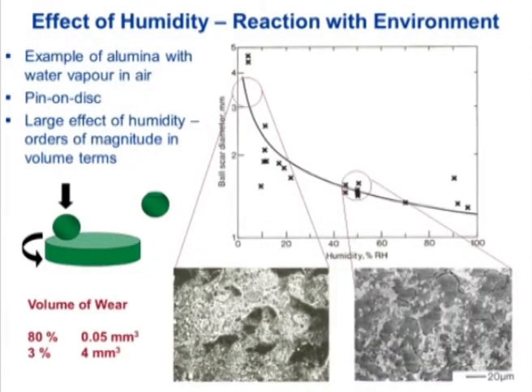An example of the effect of different test variables is humidity. I mentioned this, and it is quite surprising how big an effect you can have. This is alumina on alumina, and there's water vapor in the air, and it's carried out in a pin and disc geometry, so you're rubbing a ball against a disc, and what we're measuring here is the wear scar that appears on the ball.